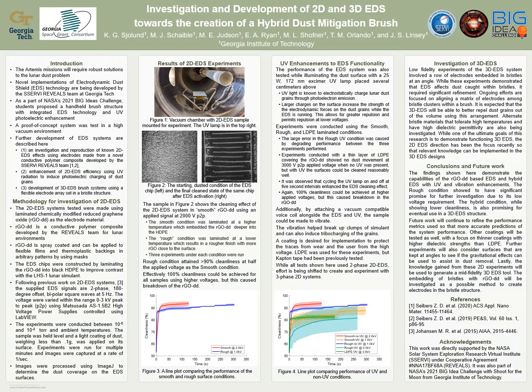Experiments involved the use of HDPE samples with interdigitated electrodes of RGO laminated into the surface. All experiments were conducted in vacuum between 10^-6 and 10^-8 torr. Further details of experimental conditions can be found in the methods section on the poster. Two surface finish conditions of the sample were considered, rough and smooth.